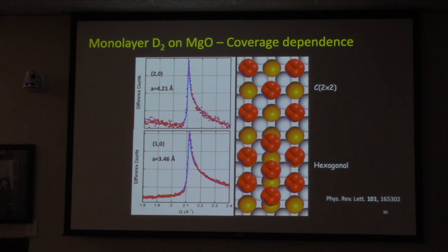Again, these are single layers, and they're different densities. And so the lowest, it turns out that at low densities, it has this what's called centered 2x2. So it doesn't sit on every lattice site. It sits on every other lattice site, and there's one molecule in the middle. So that's the nomenclature. But actually, as you increase the number of molecules in your cell, the chemical potential, it actually forms a hexagonal phase.